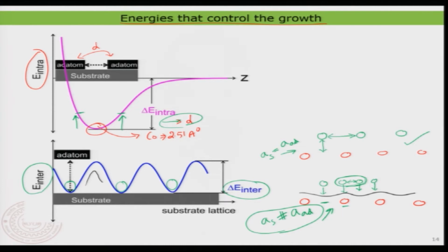So, that means you can see if the atoms of the adsorbate layer need to be compressed or stretched, then the total adsorption energy is going to be lesser compared to that when the adsorbate add layer lattice and that of the surface lattice are matching well with respect to each other. Well, that is a kind of qualitative summary of that, and now you have to basically play with these two parameters to finally form the add layer itself.